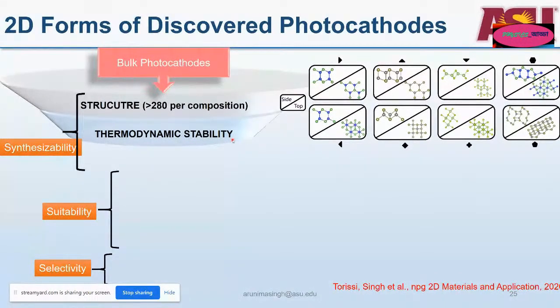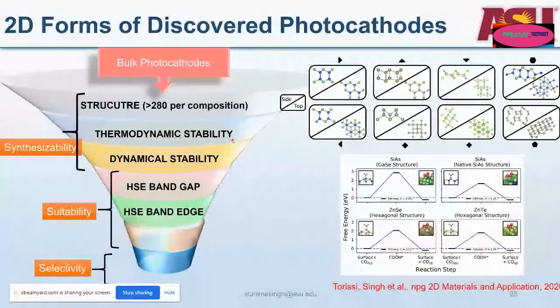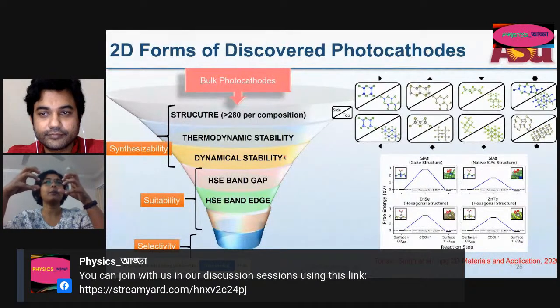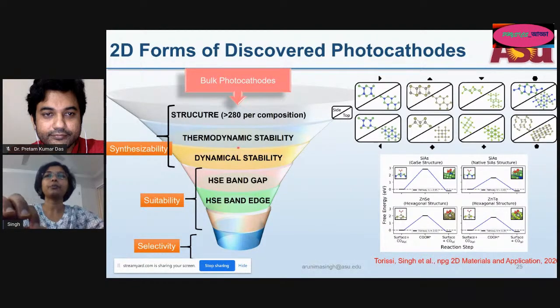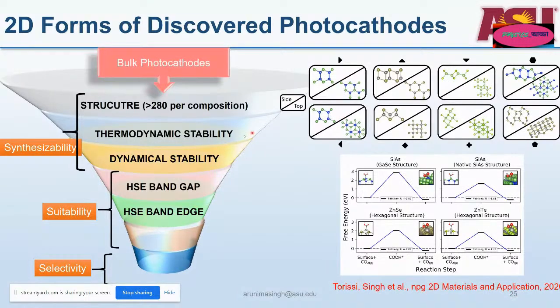The two-dimensional materials which were thermodynamically stable need to have a formation energy within 0.2 eV per atom with respect to the bulk form, which has been ascertained by certain heuristic measures by a couple of studies in the literature. And then we looked at the phonon spectra to see if it's going to be dynamically stable. So if I take a two-dimensional material and stretch out two of the atoms in its lattice, for example, and keep stretching, there should be restoring forces to bring those atoms back in. That can be seen in a phonon spectra. If there are no restoring forces, the phonon spectra is going to have imaginary modes. And we found several structures which we considered to be dynamically stable.